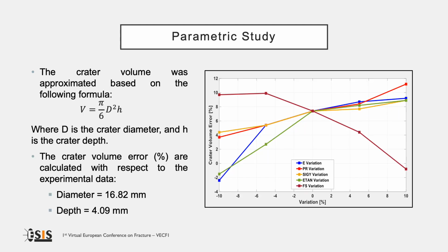A parametric study was performed by varying each single input parameter in the range between -10 and +10%. The crater volume was computed using the formula displayed in the slide, and thus also the error with respect to experimental data was calculated. It was found that if the elastic modulus increases, the crater volume increases, and thus the error. This consideration is also valid for the Poisson ratio, the yield strength, and the tangent modulus. Instead, if the failure strain increases, the crater volume decreases, and thus the error.